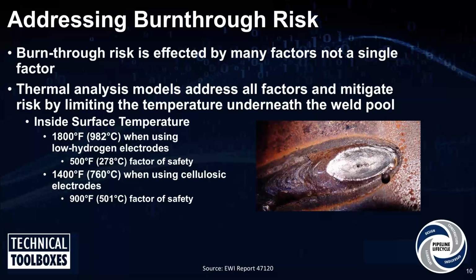The reason for the difference there mainly goes back to the electrode type, and that cellulosic electrodes, they make a welding arc with a lot of hydrogen, and that hydrogen increases the penetration of the weld arc and the weld pool. So because they had that increased penetration, this limit was decided to have an added factor of safety to reduce that inside surface temperature even more.